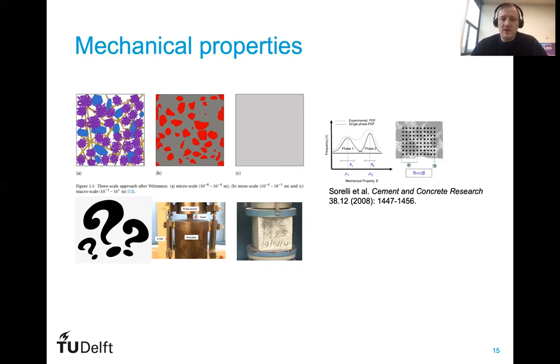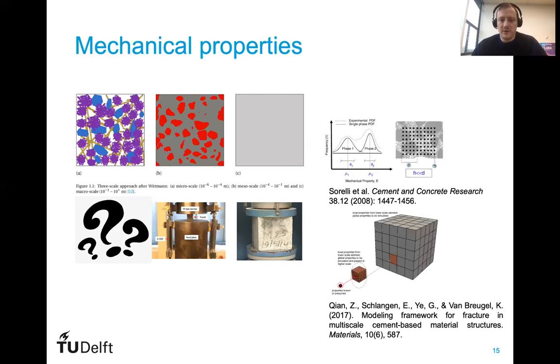What we get from nanoindentation is the elastic moduli of different phases, but we don't get the strength properties. On the other hand, at Delft, a colleague of mine has developed a multi-scale modeling framework already some years ago, whereby we would be able to go from the microscale all the way to the macro scale by passing properties calculated at lower scales. However, for this, we need to have reliable estimates of properties of different hydration phases at very small scale, which is generally not available.